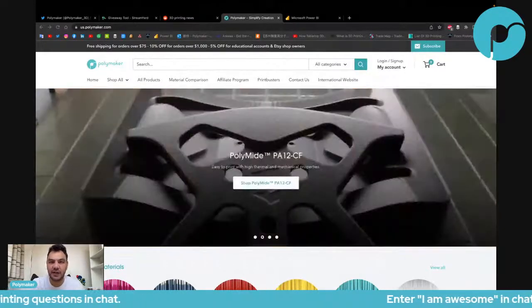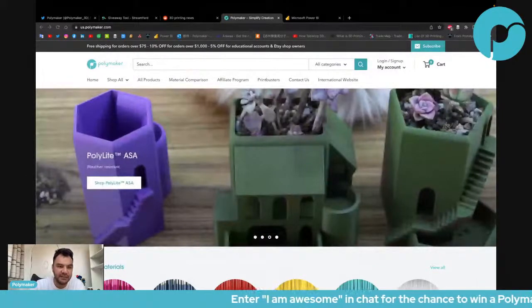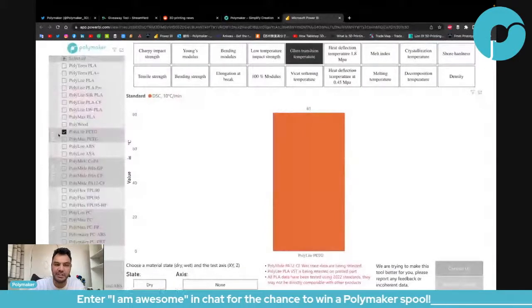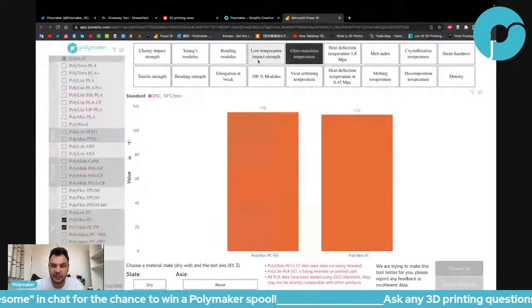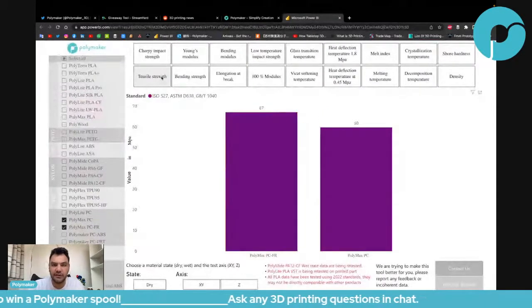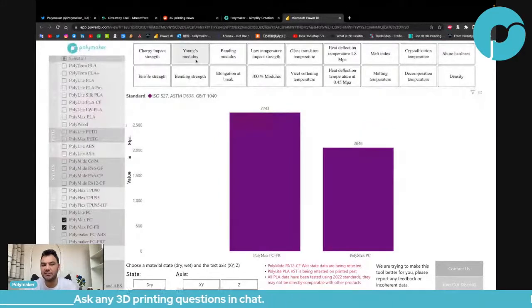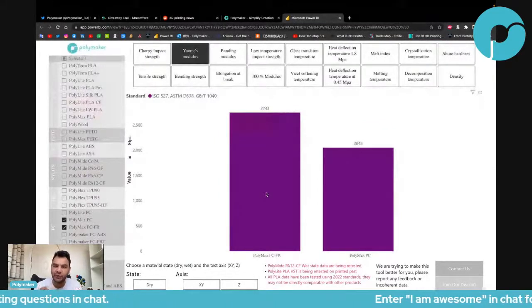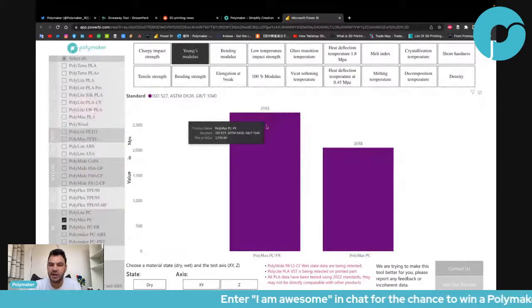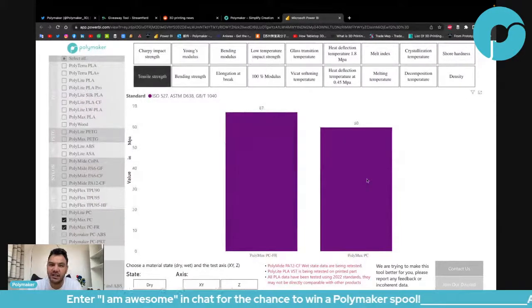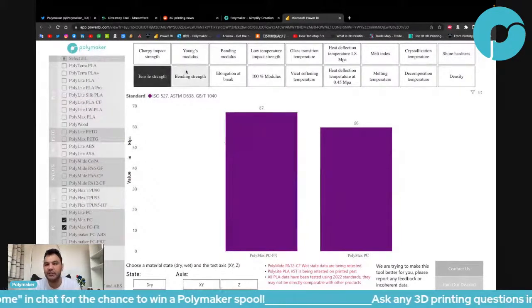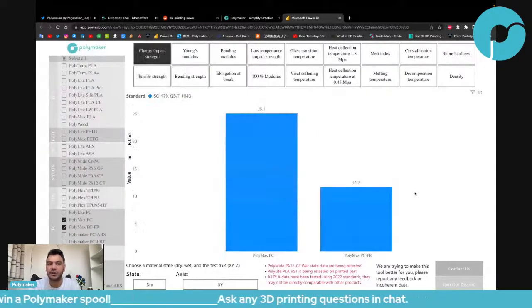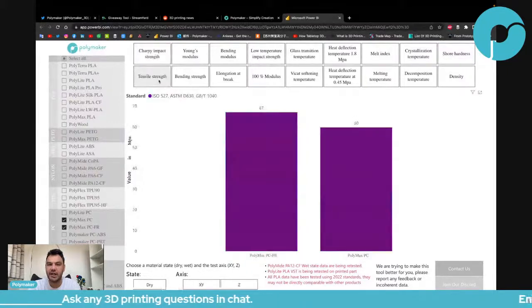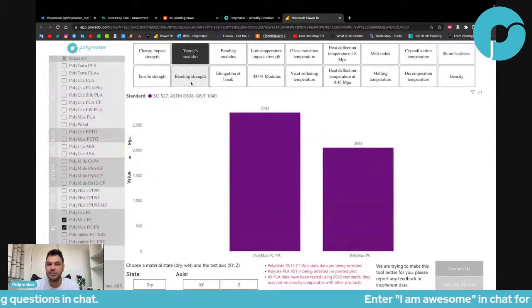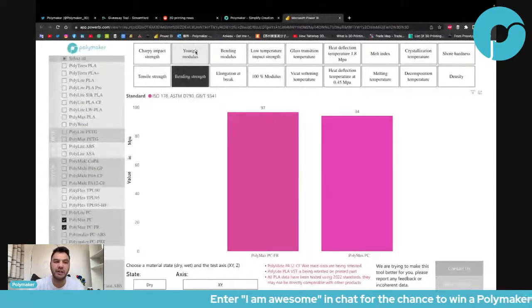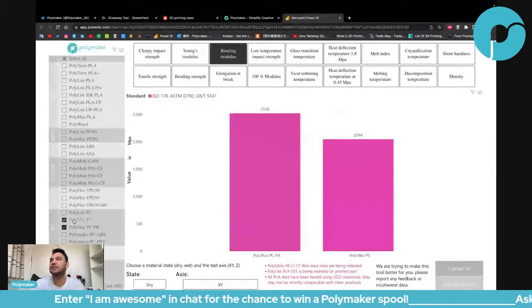If you have a look at our PCFR, the FR additive will make the material much more rigid. If you check, for example, the tensile strength, or even the modulus of our Polymax PCFR, you see that the FR additive is making the part more rigid, so it's stronger than our Polymax PC, but I do think it's less tough. So let's check. Yeah, you can see that it loses its toughness. So it's a compromise between being stronger and more rigid. You can see the Young's modulus, maybe the bending modulus as well, so it resists deformation much more. Whether you call it brittle or not, that's up to you.